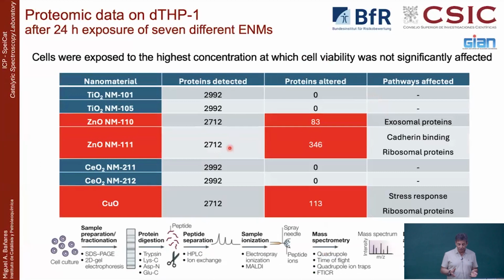What was happening in these cells? We were looking at 2,000 plus proteins, and there is software for that, of course. The interesting thing was that for the reactive materials like copper oxide and zinc oxide, they saw a number of altered proteins. And the less reactive materials like titania or ceria, which do have some activity, show no damage on the proteins. No proteins were damaged. So that was interesting because they are reactive, but they're not damaging any protein. Why is that?